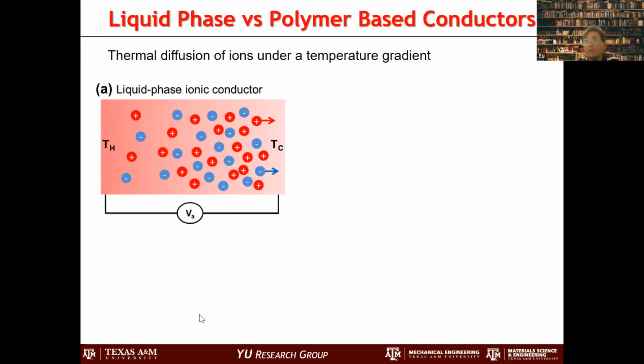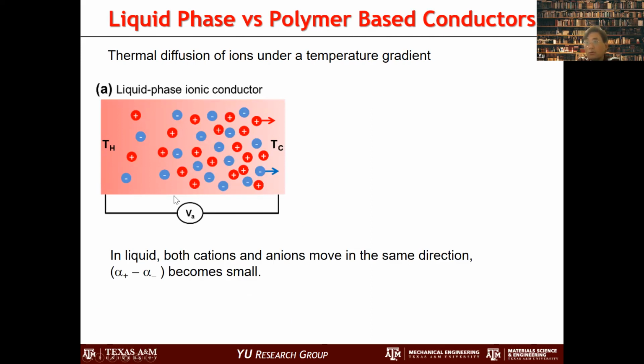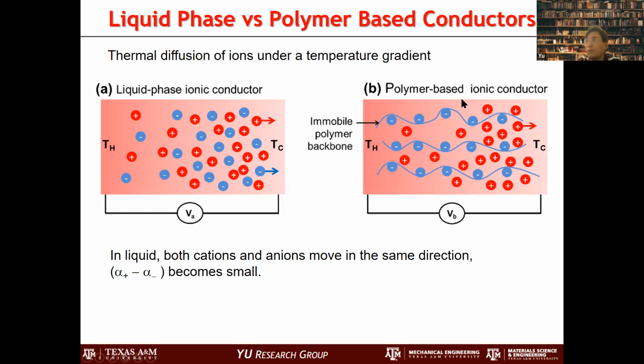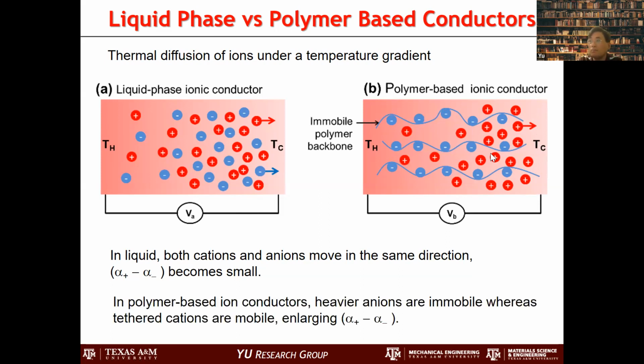And when we use a liquid phase ionic conductor, your ions actually move together. Positive and negative ions move together. So basically the numbers of positive and negative ions are about the same. So the voltage is proportional to the difference, but this is not that large. And if we have a polymer-based ion conductor, then negative ions are tethered, attached to the backbone. They are heavy, so they are not moving well. So only the mobile positive ion is moving well. So you do have a large difference in the number of positive ions. So in that case, we can develop a much larger voltage for a polymer-based ion conductor.